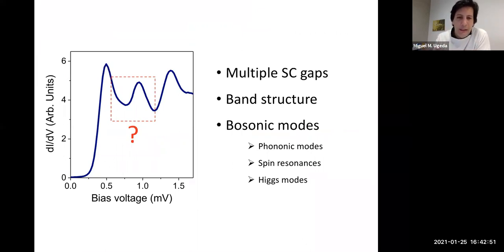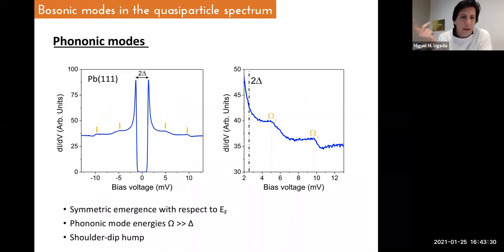So the most likely explanation is that we are dealing with a bosonic mode. That's something quite common in superconductors. But the problem is which one it could be, because there are several types of bosonic modes, and some of them are typical just of unconventional superconductors. The most typical ones are phononic modes, Higgs modes, or spin resonances. This one, as I will show you in a second, is intrinsically related to the presence of spin fluctuations, magnetism in superconductors. So, yeah, let me give you a few words about the phononic modes.